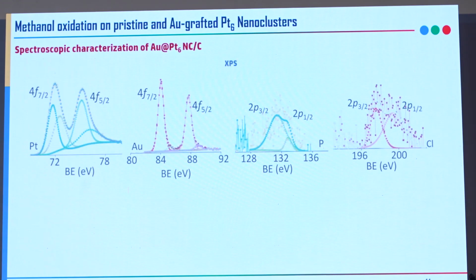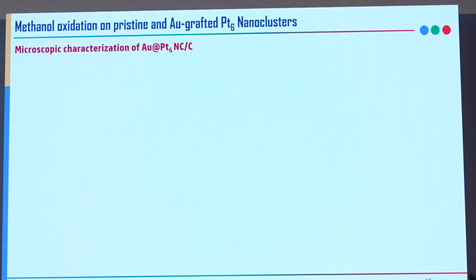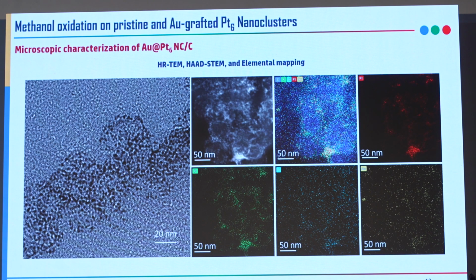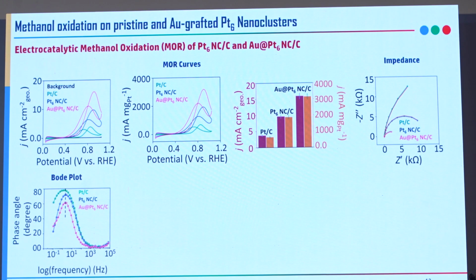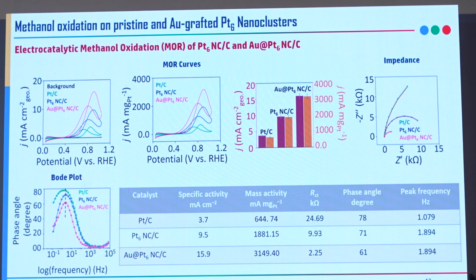So after this Au decoration, we have used XPS analysis for characterization, and the microscopy analysis also revealed the formation of Au atoms. And after this preliminary characterization, we have used these Au decorated nanoclusters for the electrocatalytic methanol oxidation, and we could find a better electrochemical activity in terms of mass activity and specific activity. These are the impedance spectroscopy and Bode plot and summary of this methanol oxidation reaction.